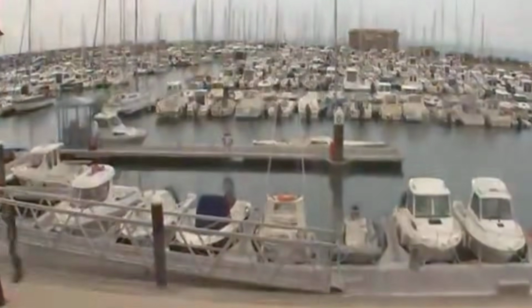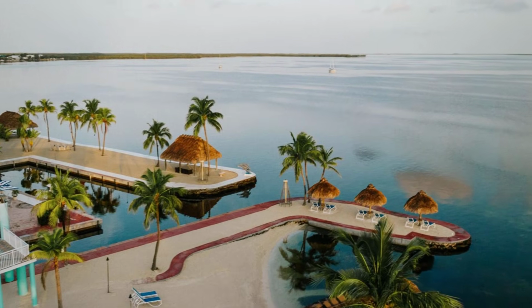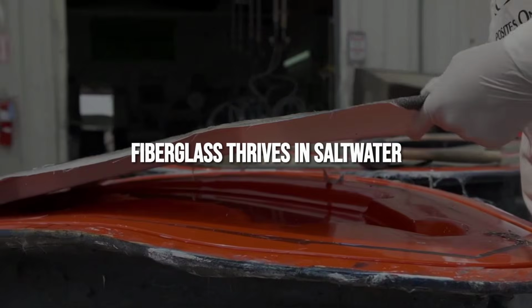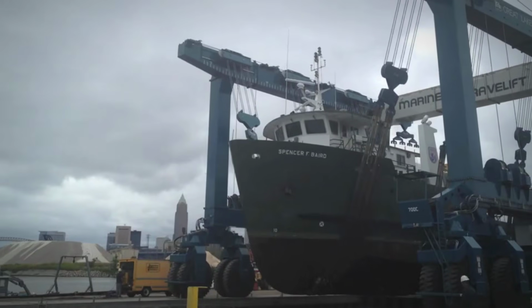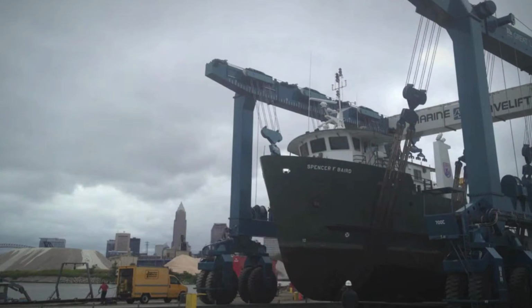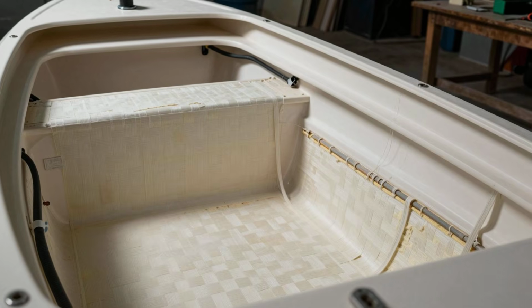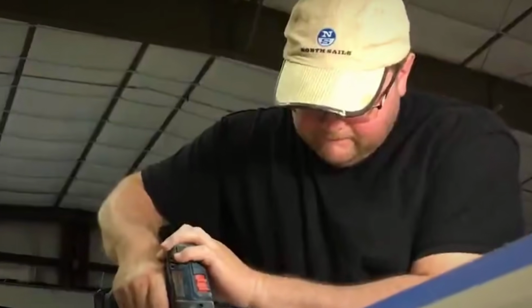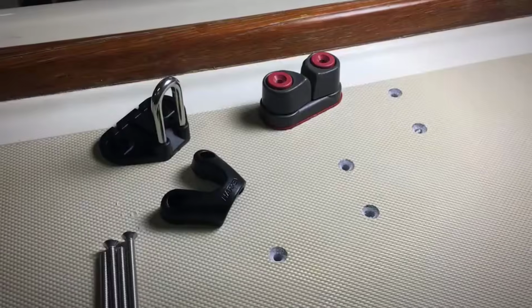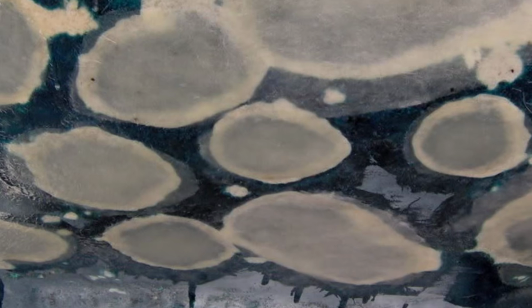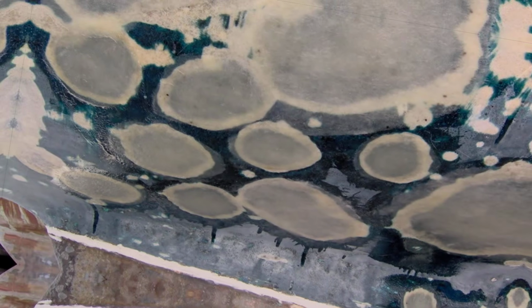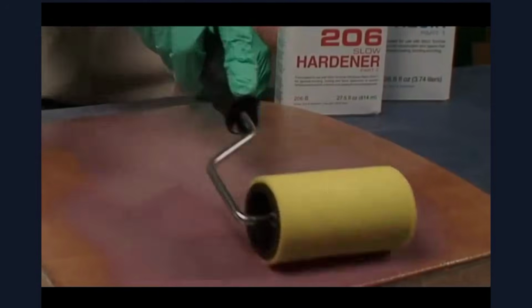conditions by decades. If you are running offshore saltwater, keeping the boat in a slip, and operating in warm coastal water year-round, a fiberglass hull built with vinylester resin throughout the laminate, hauled annually, and protected with an epoxy barrier coat and anti-fouling paint is the correct answer. Fiberglass is not part of the electrical circuit. It does not require anodes, nor does it require isolation from dissimilar metals. Its primary threat, osmotic blistering, is entirely preventable with proper barrier protection and an annual haul out.